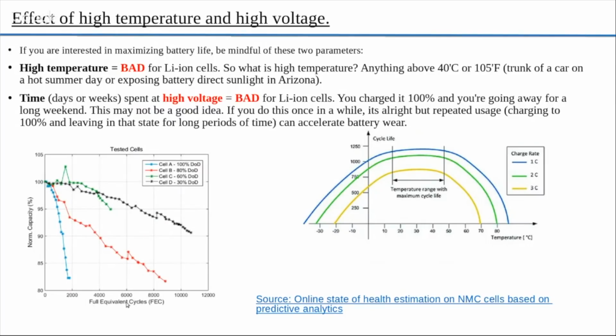So they did full equivalent cycles. If you charge and discharge 100% all the time, you'll reach 80% capacity in less than 2,000 cycles. That is less than 5 years maybe, right? And that's 100% depth of discharge. But if you do 80%, you're looking at a lot more cycles. If you do 60%, that's even better. So ideally, you want to charge to 70 to 80%, then you're looking at easily 8 years of life.